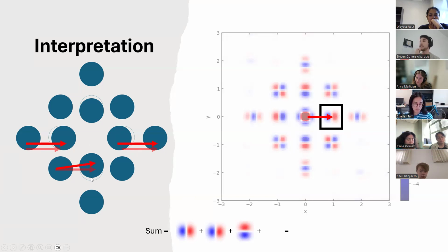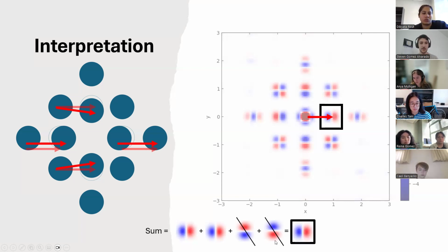So one of the vectors is actually this guy. So this atom and this atom had a change in their relationship, where the final vector has actually been moved up. Okay, so what that creates is an upward shift at this coordinate in the PDF space. Okay, so it's these two plus this upward shift that's all being added at this position. But to cancel it out, there's another one. That's where the change in the interatomic distance has moved down. Okay, so that imparts a downward shift that then cancels out. So effectively, what we're left with is this expansion.